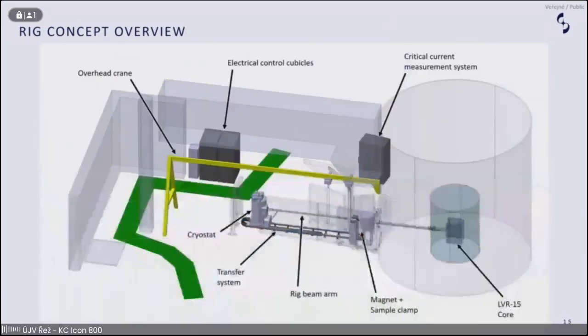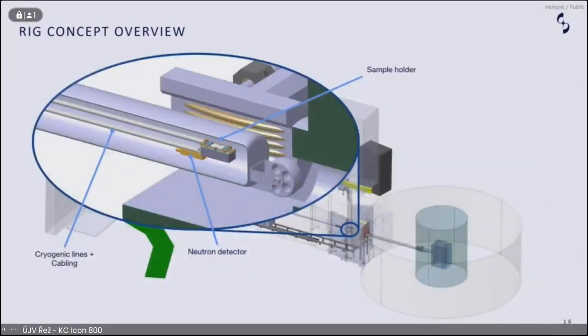So this here is the rig arm, and we have our sample right at the end there. This sample is very small, around 5 centimetres by 2 centimetres, and we'll have our REBCO tape there, and our connectors there. This is where our sample will be, so we need to put our sample as far into the core as we require to get the irradiation we need.